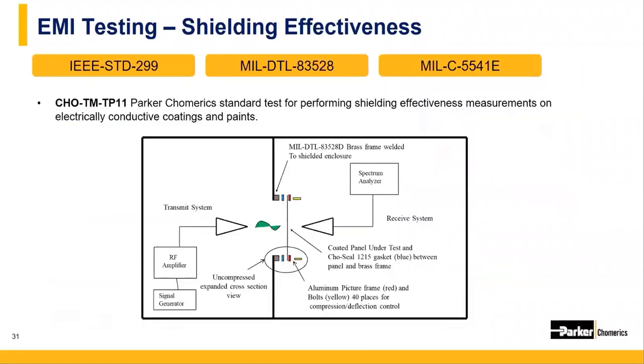EMI shielding testing for coatings is very similar to that of sealants, gap fillers, and gaskets. A coated test panel, often one that has undergone chromate conversion coating per MIL-SPEC 5541 prior to coating, is run from low frequency testing at or below 30 megahertz to 10 gigahertz and higher for thorough testing. The test setup you see on the slide is a modified version of the IEEE 299 EMI shielding test.